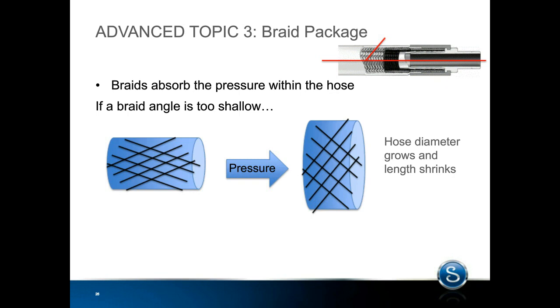And the hose also, because the material just can't be made magically, when it grows in diameter, the hose actually shrinks in length. And this can lead to some pretty catastrophic failures. First of all, the core could burst, because the core just can't withstand that kind of growth in the diameter. Or, because the hose is shrinking, it could pull the end connection out, both being, of course, very, very bad and dangerous failures. So a shallow braid can be very dangerous.